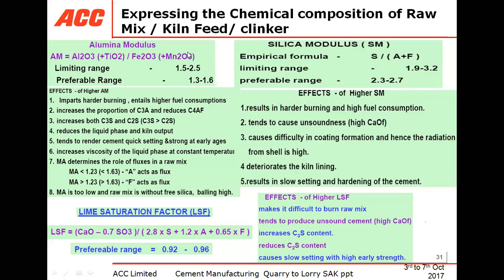There are other modulus also, the alumina modulus and silica modulus, which need to be monitored. The alumina modulus is the ratio of alumina to iron. These are the formulas given over here. And the silica modulus is the ratio of silica to the alumina and iron content. The limiting range of alumina modulus is 1.5 to 2.5, and the preferable range is 1.3 to 1.6, whereas for silica modulus the range is 1.9 to 3, and the preferable range is 2.3 to 2.7. And the lime saturation factor, a very important modulus, should be maintained around 0.92 to 0.96.